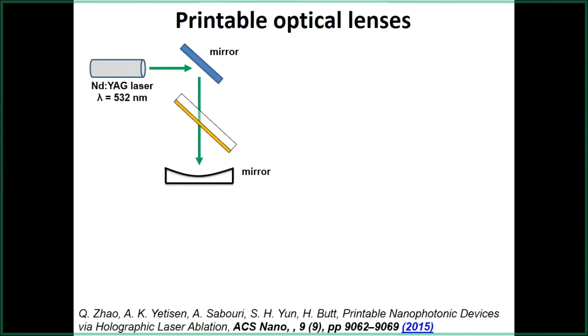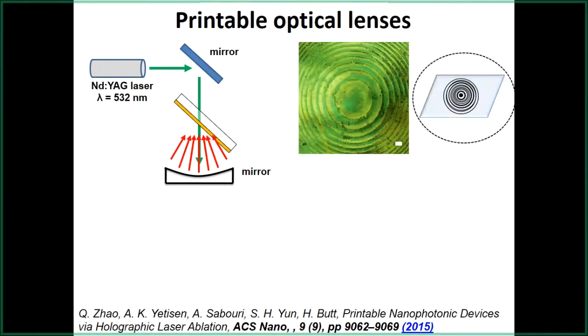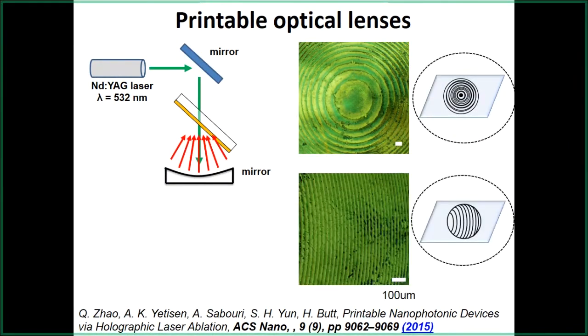Apart from just making gratings, we have also been experimenting with different types of mirrors, or in other words, we have been changing the interference patterns. So rather than having a flat mirror, if you use a concave mirror, rather than making periodic gratings, now you can get these periodic rings which are imprinted on top of your sample. In this case we used a thin film of gold. It gets imprinted in the form of these concentric rings, which actually acts as a Fresnel lens. The Fresnel lens also has a very similar structure. So this structure, which was a mirror image of a lens, acts as a lens as well.